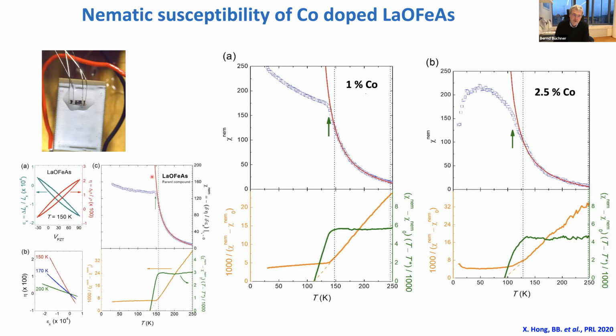This shows a divergence close to the structural phase transition. That's all well established for the other systems. Here you can see that this Curie-Weiss fit is not so bad, and you can extract the Curie-Weiss temperature, which is close to 130 Kelvin for the parent compound. And this you can do now for all these doping concentrations. This Curie-Weiss fit is more or less working also for doped crystals. What you see then is that the Curie-Weiss temperature becomes smaller.